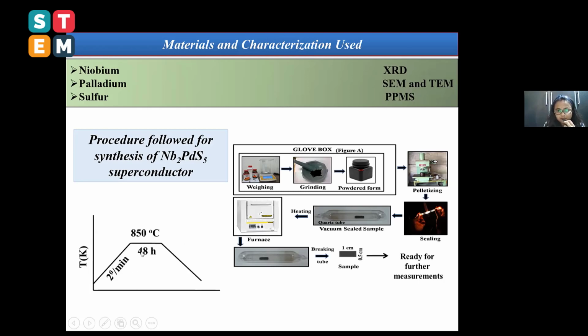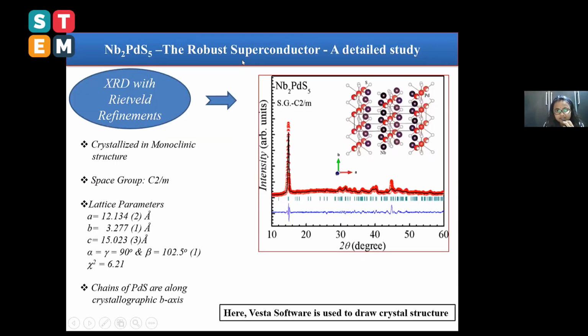This is the temperature curve followed for synthesis of this Nb2PdS5 sample. First, we increase the temperature at a rate of 2 degrees centigrade per minute, and then we hold the temperature at 850 degrees centigrade for 48 hours, and then we allow it to cool down naturally. After synthesis, we performed XRD. We fitted the room temperature XRD using Rietveld refinement, and these are the lattice parameters found for the Nb2PdS5 sample.